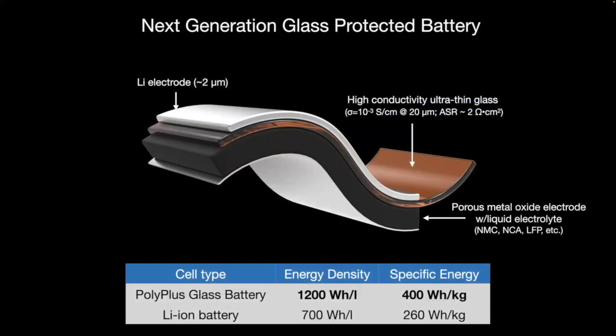And then in cross section, this artist diagram of the cell looks something like this. Again, we start with a porous metal oxide cathode, thin glass separator, and just a bit of lithium. That's a seed layer for electrodeposition on the first charge. And then we leave some of that lithium as we cycle. That should take us, relative to a conventional lithium ion, from 700 watt hours per liter to 1200, and on specific energy from roughly 260 to 400. This is still a hybrid cell. In other words, that cathode still has liquid in it. So it's kind of two thirds solid state.